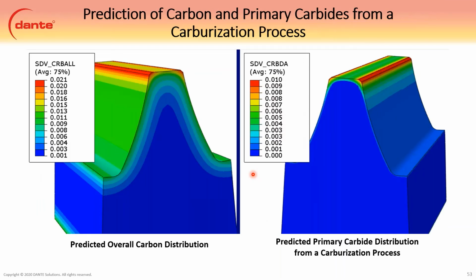This is just a still shot. Let me think about getting an animation in here now that I look at it. Anyway, on the left is the overall carbon. So you can see we're almost at 2% in the corners up here. The figure on the right is the amount of carbon that is in carbides. And you can see we got about 1% in the tip edge, about 0.5% everywhere else up on the tip. And then as we go down, we substantially lose carbides. So light carbides down here on the flank and in the core, but a bunch up here on the tip.